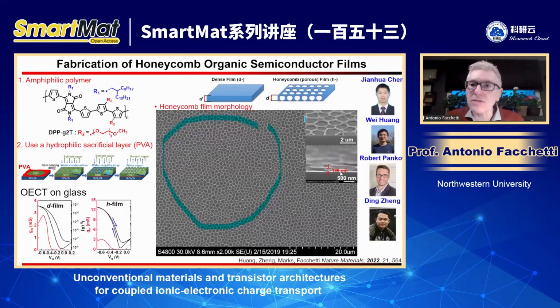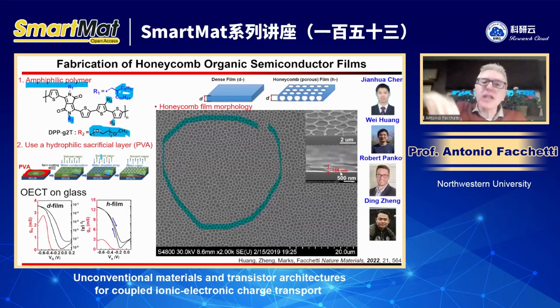And how did we achieve this very nice honeycomb morphology? By using an amphiphilic polymer, which has both a hydrophobic chain, this is here an alkyl, and a hydrophilic chain, so you need to have both. The other variation is when we prepare the film, we don't spin coat on glass or silicon oxide, but we spin coat on top of a film which has a little bit of polyvinyl alcohol. Polyvinyl alcohol is very hydrophilic, so water really likes to condense on the substrate, and it really helps to create this very nice morphology.